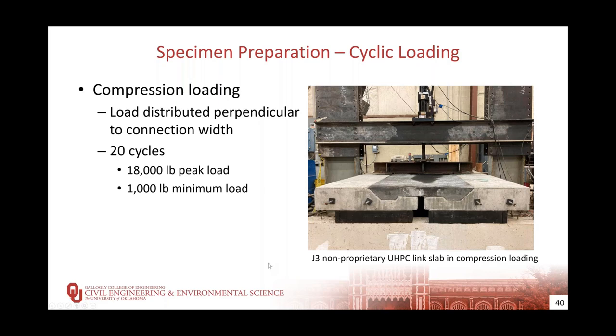They were supported at the connection ends along those edges, and the steel beam was rotated 90 degrees to have the slab bend about its other axis. The base load for each cycle stayed at 1,000 pounds, with the peak load reaching 18,000 pounds, which is the cracking load for the AA mix. Again, due to mechanical issues, we only performed 20 cycles for that high loading, as compression loading of the joint is not necessarily critical to its performance. Once this was done for both specimens, we now have one loaded slab and one unloaded slab for each connection material.